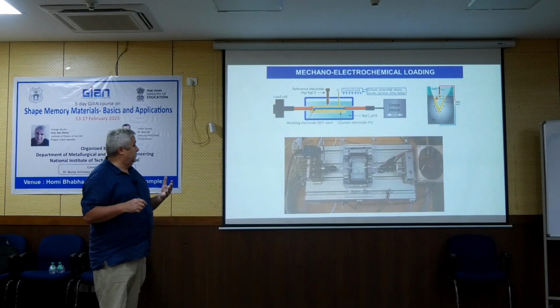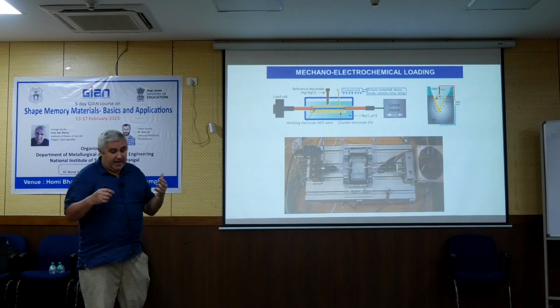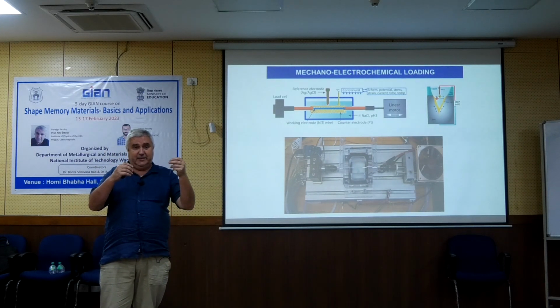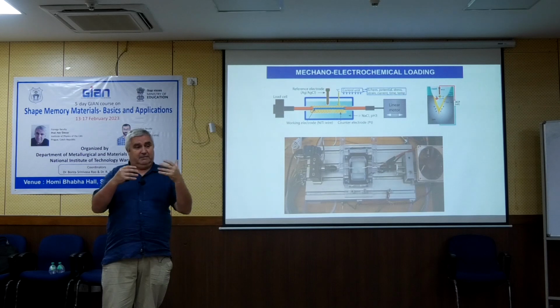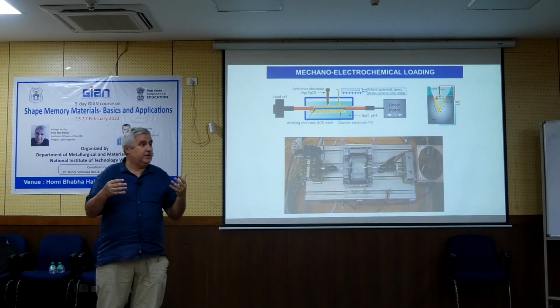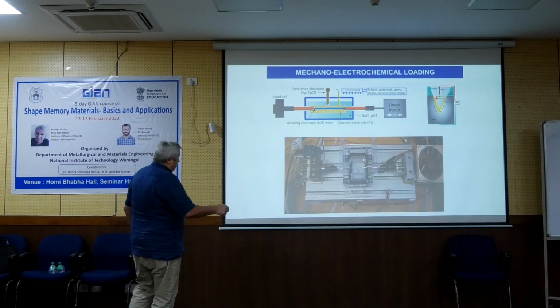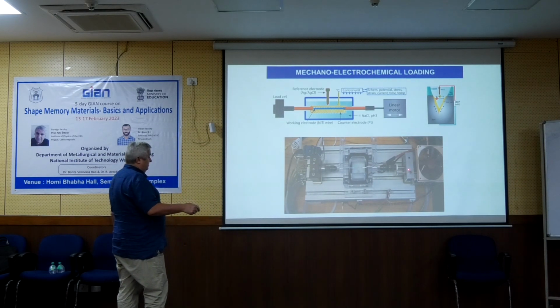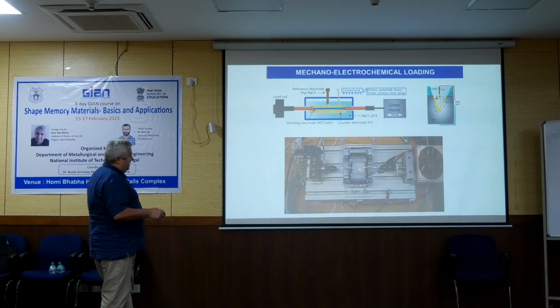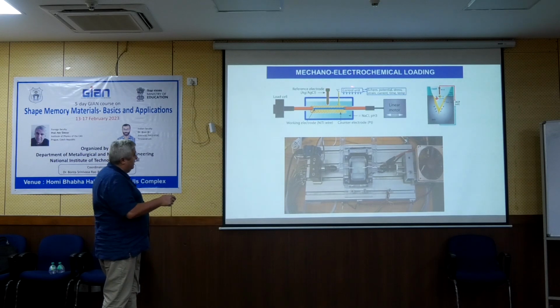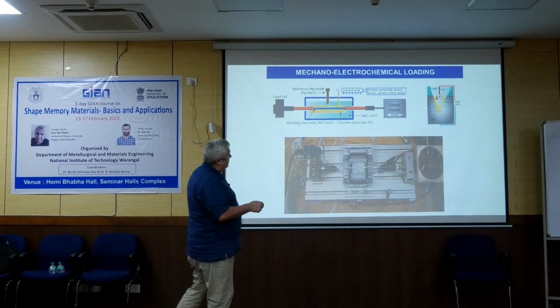But immediately when the bare metal is open to the fluid, the potential is changing. So we thought we might be able to detect this cracking by detecting the electrochemical potential. But we needed to make the experiment for that. So the experiment looks like this, where there is a tester, there is an electrochemical cell, the sample is one electrode, another electrode is just submerged into this cell, and we measure the potential between the fluid and the electrode, which is schematically shown here. And this is just a schematic picture which shows the metal matrix.